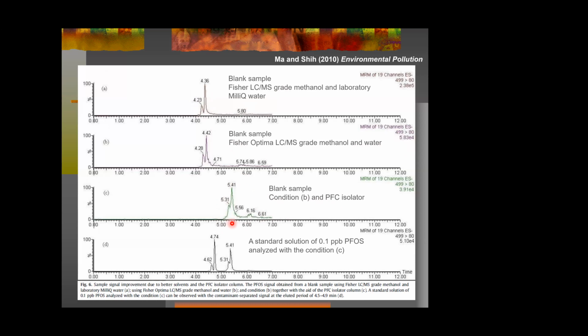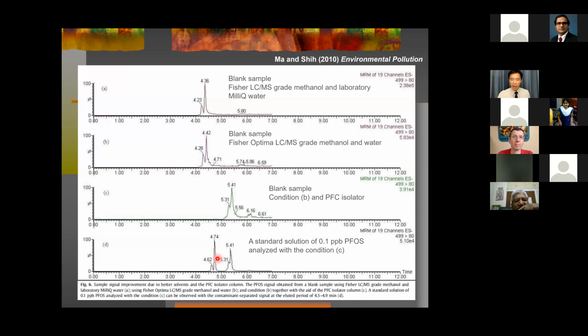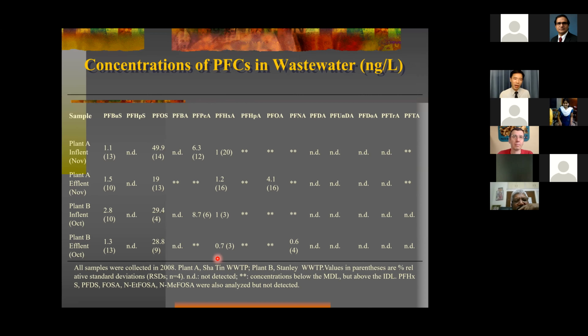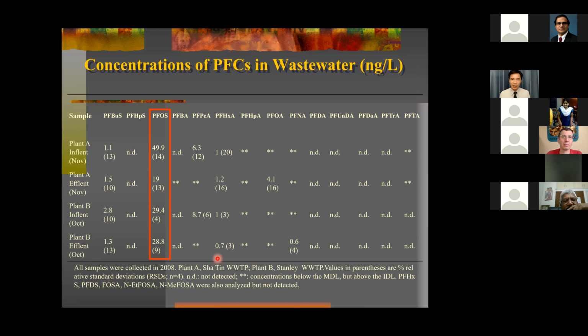We can bring the signal to a later phase. In that case, this represents the signal coming from the instrument. So when we have the real sample injected, the real signal will come out at a different timing. In that case, you separate the background signal from the signal that you really want to measure. We spent almost 1.5 years to make the skill good enough to operate. Eventually we used it to measure the wastewater, to see whether it has this type of compound. And the answer is bingo.